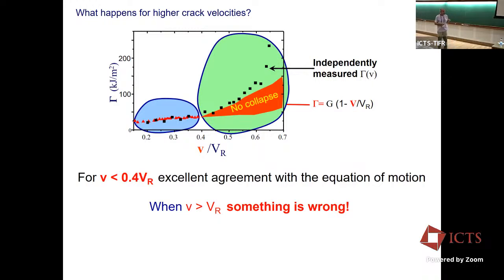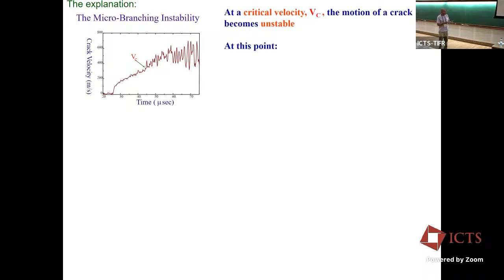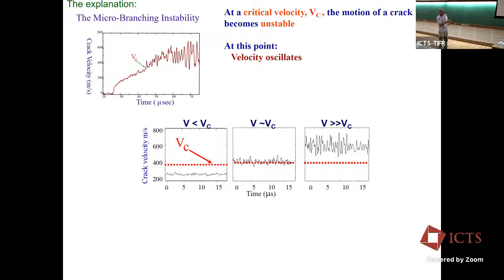So it's telling us something is wrong. And now I'll quickly tell you what is wrong. What happens is that our simple crack becomes unstable. It undergoes an instability, which we called microbranching for reasons that you'll see in a moment. So at the point where the crack becomes unstable and the equation of motion stops working, this is the crack velocity as a function of time below this instability threshold, and we see that it's clean data, to experimental accuracy. Now it starts to get a bit noisier as we get to this critical value where everything breaks down, and it becomes really messy